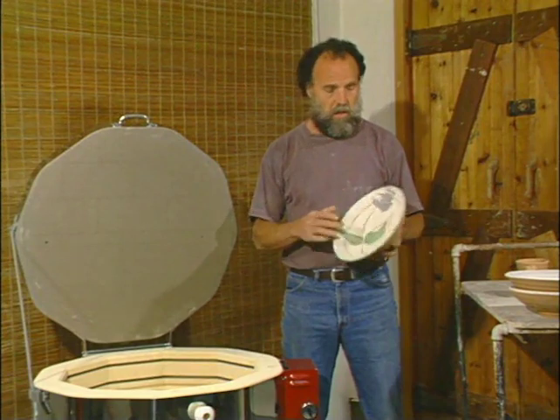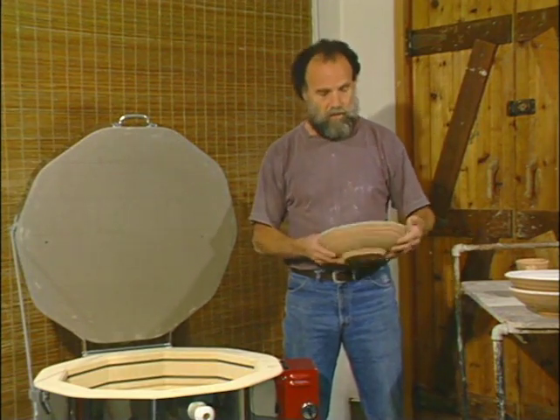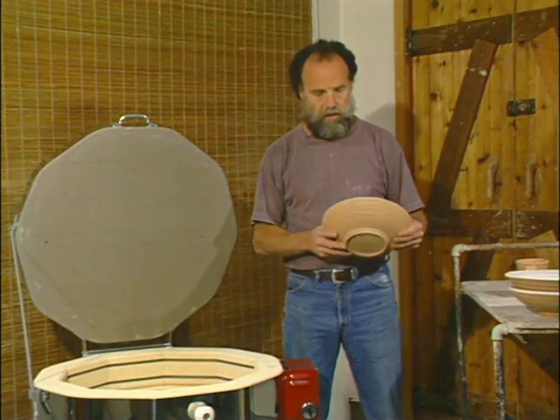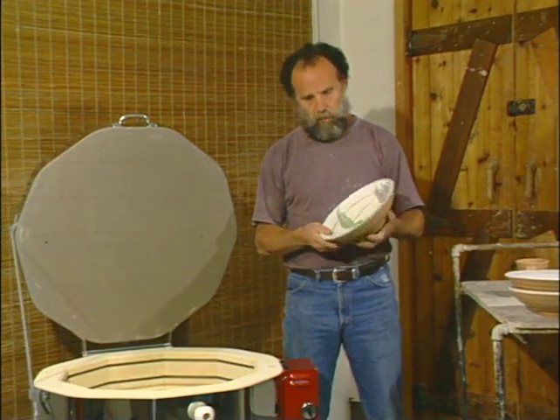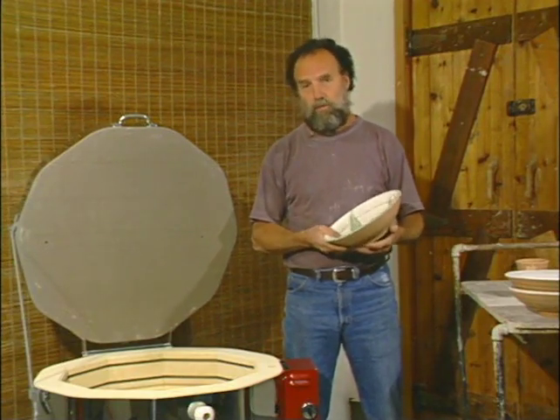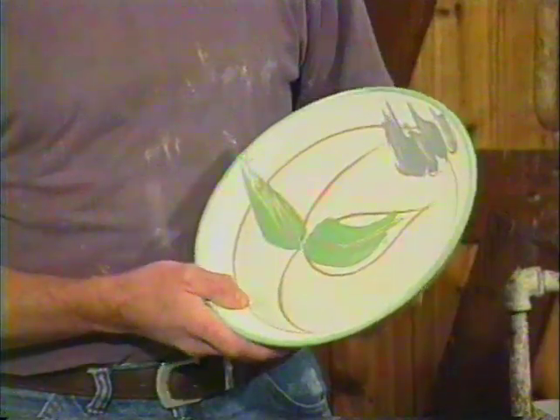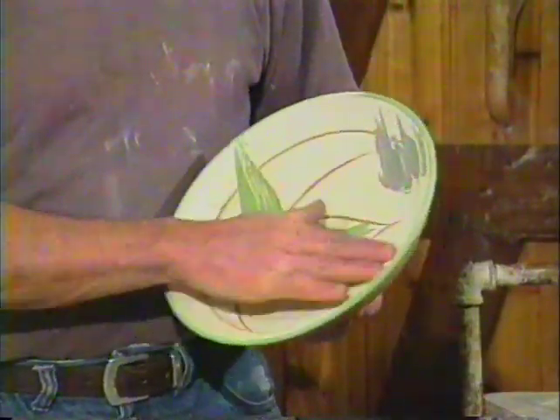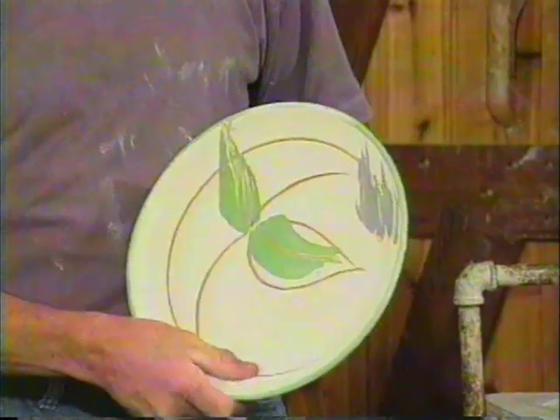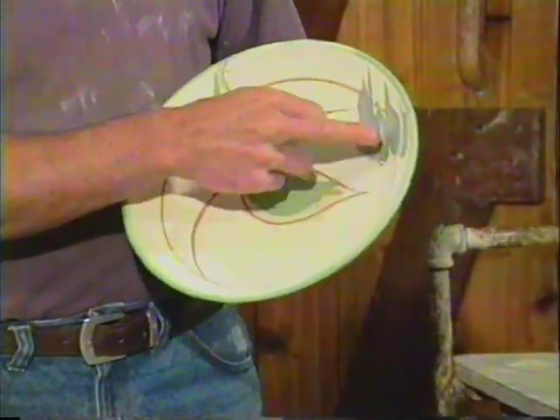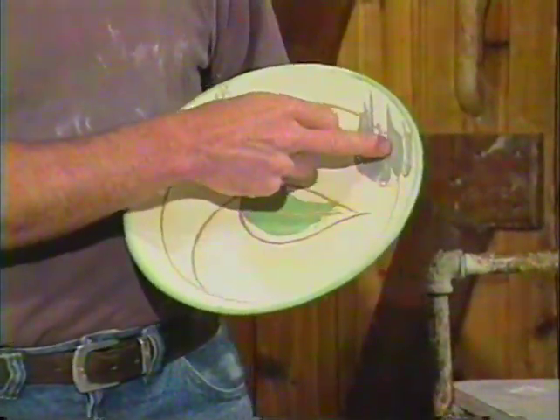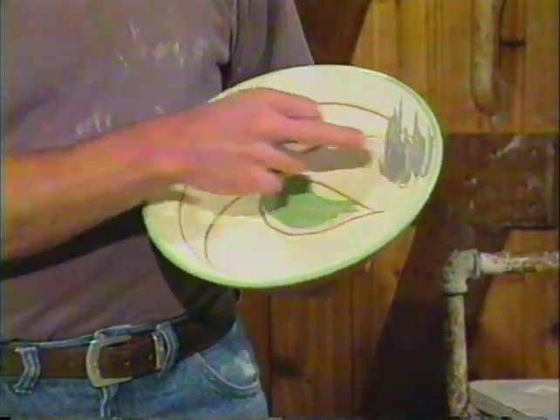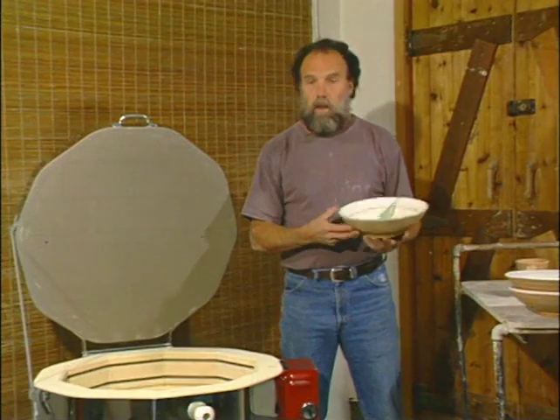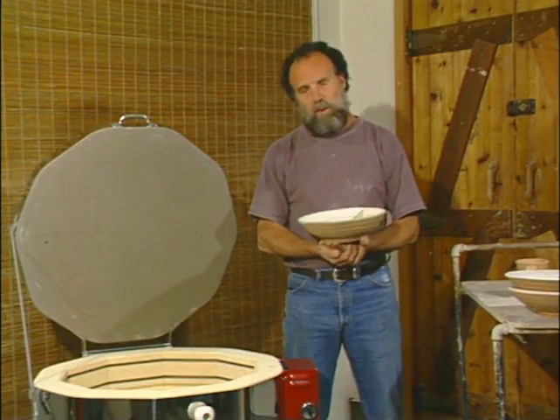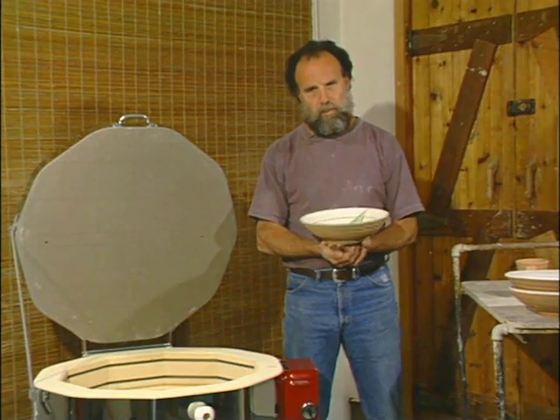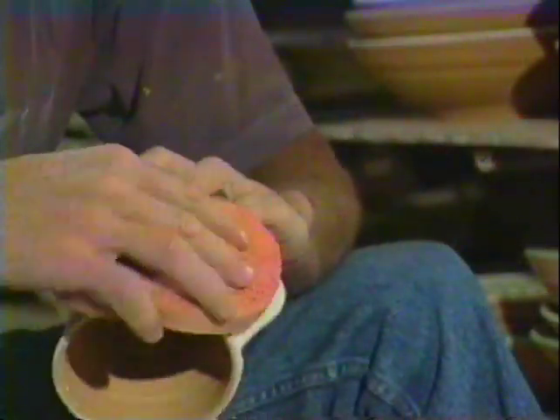As you can hear, we've done quite something to increase the mechanical strength of this clay. It's now strong enough to be able to withstand the handling that it's going to have during the glazing process. You can see also that the slips are fired hard onto the surface of the bisqueware, and that the colours, when we put this blue on, it was rather an anonymous grey colour, and it's now showing quite a nice blue. The next stage is glazing, and in preparation for that we need to put some wax on the bottom of some of the pots. So let's go do that.